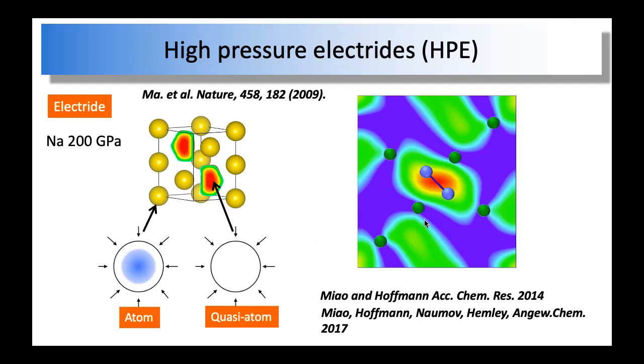For example, the lithium case is actually more complicated, right? The lithium electride was first discovered by experiments, and for quite a while, people didn't even know its structure. And there was a lot of crystal structure search work, and at about the same time, people in China and people in Britain found this structure. But when you calculate the electronic structure with DFT, you find something very puzzling, because it also has open sites.